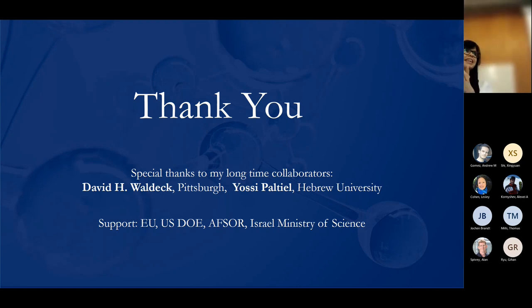Okay, there are several issues here. I spoke about small molecules, really small. The reason is there is another effect: if electrons go through molecules or polymers, and we have results on this, they get scattered. There is scattering in the polymer, and the scattering reduces the spin polarization. With chiral polymers up to 100 nanometers, we saw an increase in the spin polarization, but it was not a monotonic increase. It started to level off. I assume that with a polymer like the one you mentioned, it will level off and remain constant, and will not go beyond it because of the scattering inside the system. So optical activity isn't enough to describe what's going on. If you go beyond the single molecule level, you need to take scattering into account.